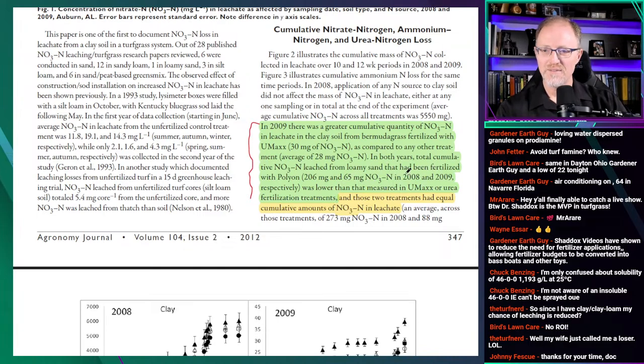Read this again. So nitrate leaching: in both years, total cumulative nitrate leached from loamy sand that had been fertilized with Polyon was lower than that measured in UMaxx or urea fertilized treatments. And those two treatments had equal cumulative amounts of nitrate in leachate. You see how she kind of threw that in there? I wonder if she did that on purpose. She said she didn't really have to throw that in there, but I like the fact that she did. The UMaxx and urea had equal cumulative amounts of nitrate in leachate. She just kind of slid that in there.